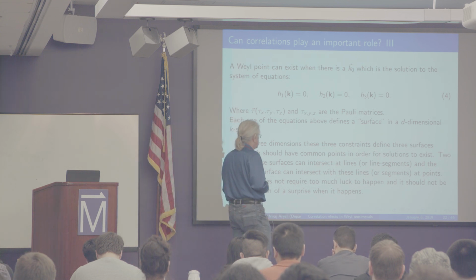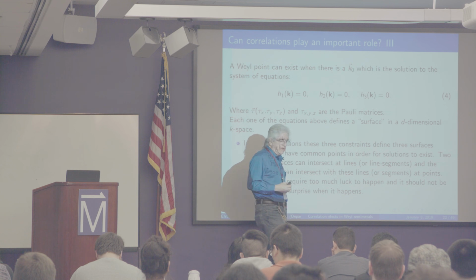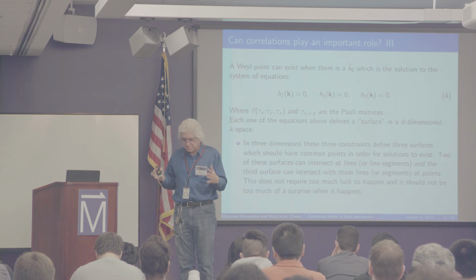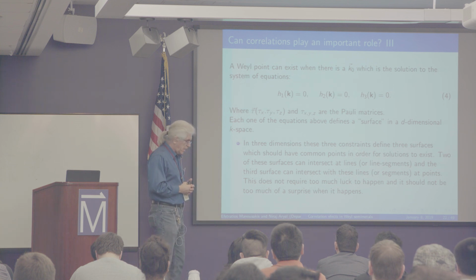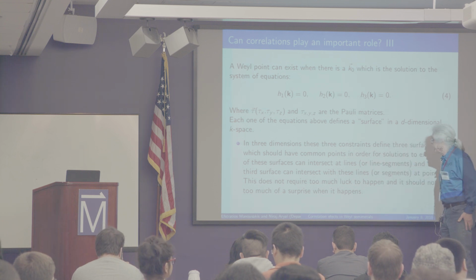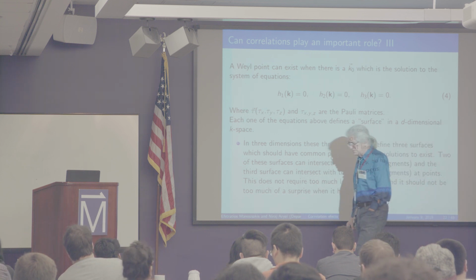So in 3 dimensions, given the fact that you have a Brillouin zone which is bounded, and you have plenty of bands going around inside this small room, finding Weyl points in any material wouldn't surprise me. The only question is, are they going to be relevant? That means, are they going to give you the low energy physics of the problem? That means, will they be close to the Fermi level?